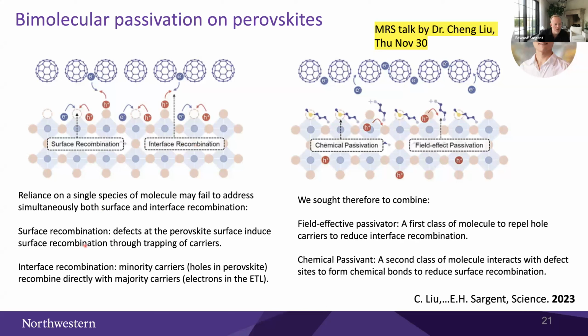The first is surface recombination contributed at surfaces by the presence of defects. And the second is just the natural interface recombination that could occur even without defects, but it occurs because of a reasonably high accumulation of electrons that can meet up with holes in the active layer. And so Cheng in this work sought a strategy that could unite field effect passivation to keep the holes away from the interface, and then also a chemical passivant to deal with the passivation of the chemical sites.